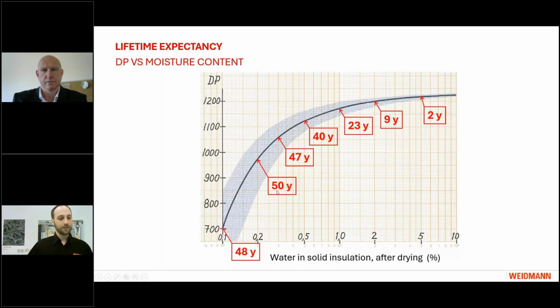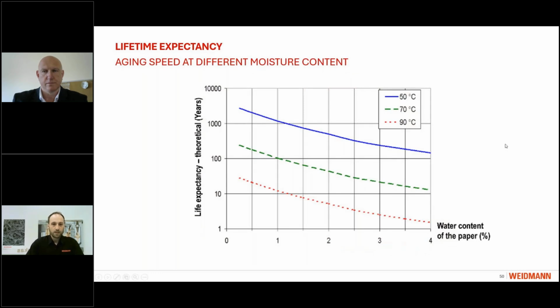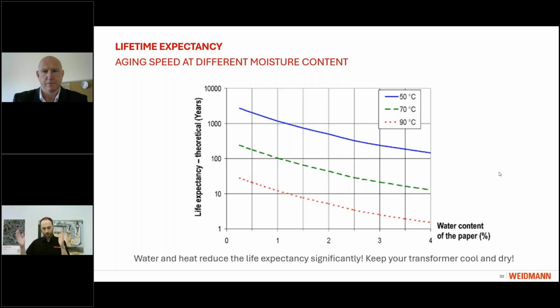Nevertheless, you can really see in this graphic that it is crucial that we are dry, and we should not fear an additional drying cycle if done correctly with the minimum amount of degree of polymerization decrease, because the water and this autocatalytic reaction are really the detrimental factor in lifetime expectancy. So, as a message for you guys to take home, and really nicely summed up in this graph, we can say, what is required to do a lifetime expectancy in the maximum sense? And the answer is water and heat reduce the lifetime expectancy significantly. And therefore, if you want to have a long-living transformer, you have to keep it cool and dry.